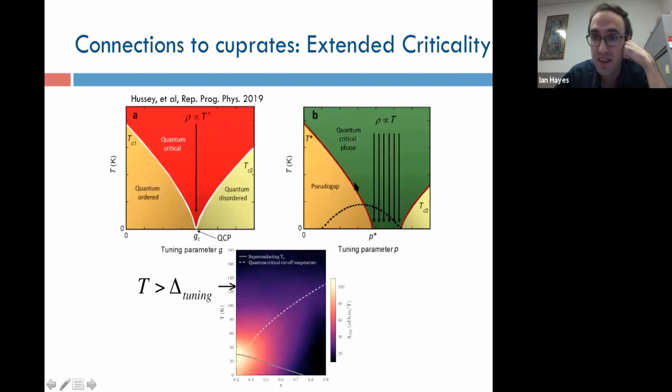And this is nicely laid out in a paper by Nigel that contrasts the way criticality seems to emerge in pnictides and cuprates, whereas in the cuprates you seem to have an extended region of some sort of critical behavior going up to the edge of the superconducting dome. The pnictides up until now have seemed more conventional critical systems, in the sense that things are concentrated really near a point where the antiferromagnetic order ends. I think one takeaway of this observation is that there is more of a connection between these two scenarios than it originally seemed.